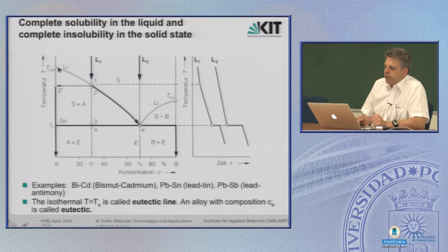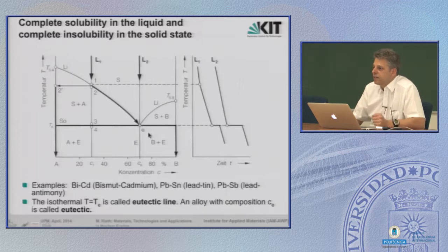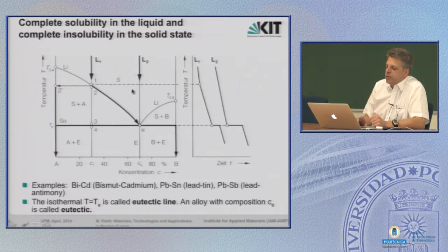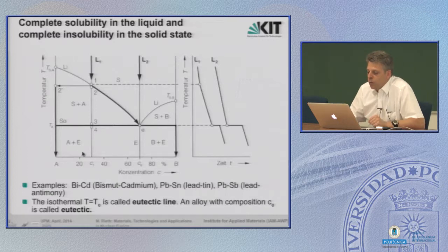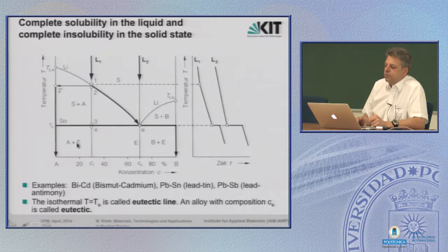The line where we have a transition from liquid to solid, the liquidus line, shows a minimum at some point of concentration, and otherwise here we are liquid, here again we have solid and liquid phase, and only here we have a completely solid phase. The point here where we have a minimum of the melting temperature, this is called the eutectic composition. So this is the eutectic line here, and as soon as you come down in temperature below this line, the material forms this eutectic composition, that's something very specific, and the rest which is not needed to form this phase is either component A or B.